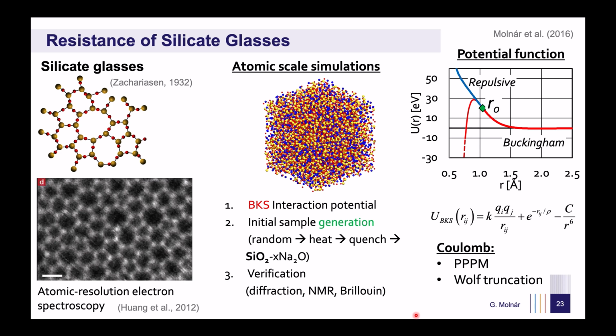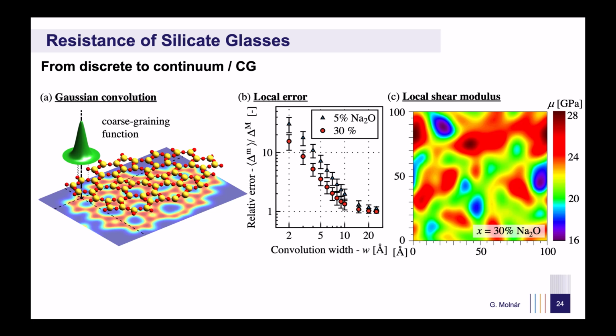To study their mechanical behavior, we applied quasi-static deformation, meaning time and temperature effects were ignored. Coming from a continuum mechanics background, our goal was to bridge the gap between atomic scale results and macroscopic material properties. To achieve this, we applied a Gaussian convolution technique to coarse grain the discrete atomic data. This technique ensures both mass and energy conservation, allowing us to define continuum-like quantities for atomic scale simulations.